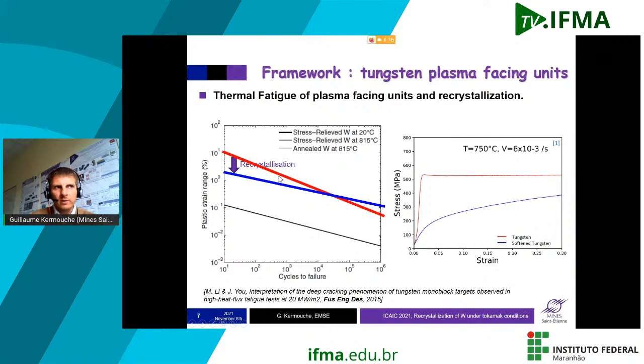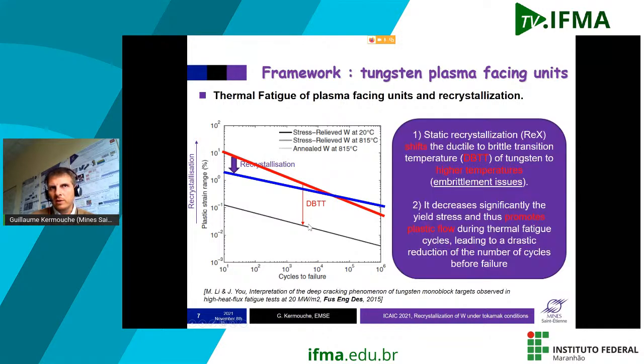So recrystallization will play on this, but recrystallization will also play on the plastic strain level because the yield stress is lower. So at each cycle, you will have much more plastic strain for a given cycle. Okay, so recrystallization clearly is not very good for fatigue. And the second aspect is that if there is some plastic strain that happens at a low temperature, finally you have to consider this curve to design the fatigue damage. Okay. And this curve is related to the ductile to brittle transition temperature. So recrystallization will play on the DBTT, okay, but it will also play on the plastic flow that happens during each thermal cycle.